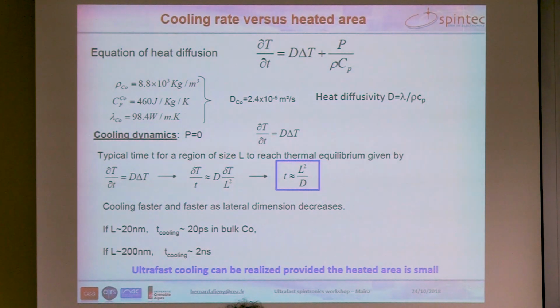So first, a general consideration about the cooling rate in a metallic material as a function of the heated area. You know that the heating and cooling is described by this well-known equation of heat diffusion, where we have here the diffusivity of the media, which is given by this expression. This is here the source term. So in that case, it will be the plasmonic antenna. This is actually the density of the media and the specific heat of the media.